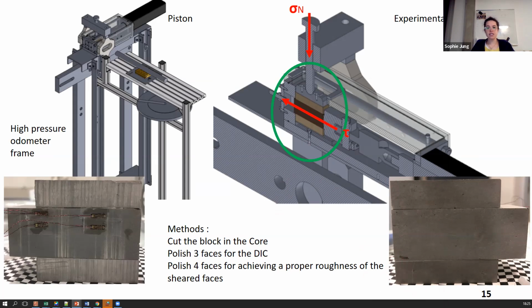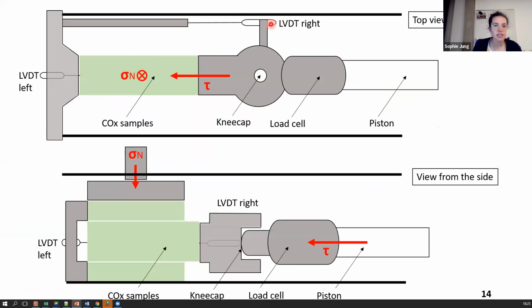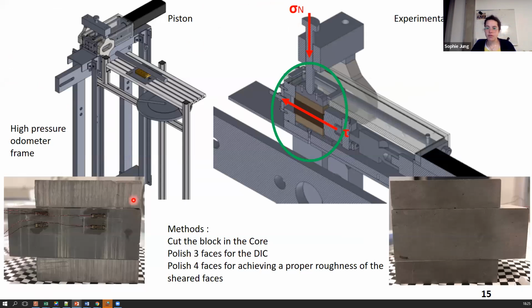There are 2 LVDTs on each side of the sheared sample. The middle one is the sheared sample. You can see it better here. 1 LVDT measures the movement of the piston, and 1 other LVDT is placed behind the block. So they measure the average displacement of the central block, and a force sensor is located here, allowing the piloting of the cylinder in constant stress. The middle block is 2 centimeters longer than the 2 other blocks, just to keep the sheared surface constant during the experiment.